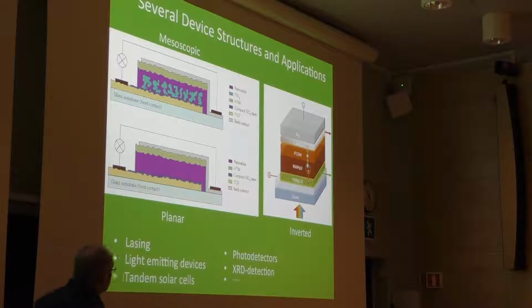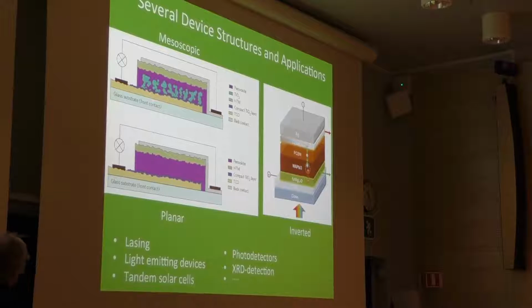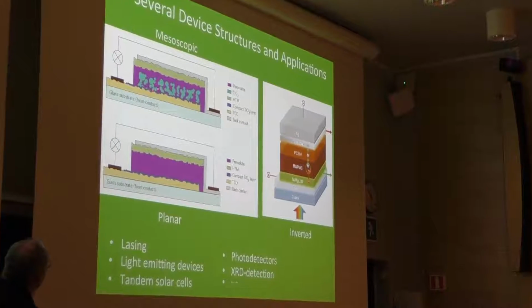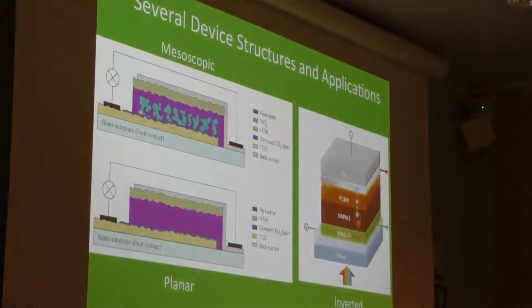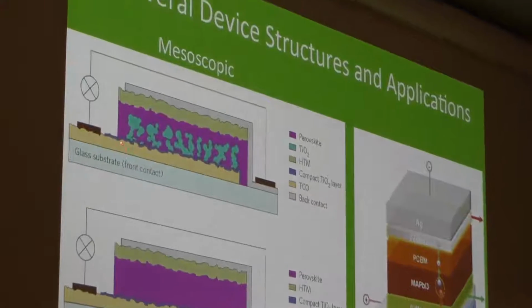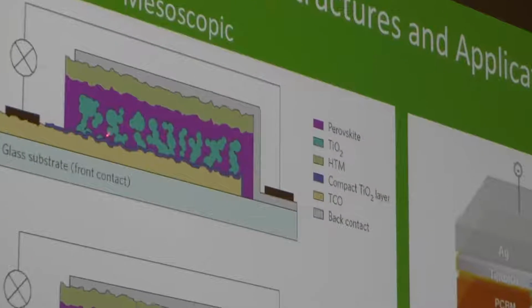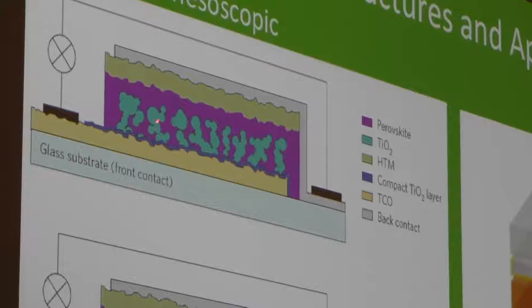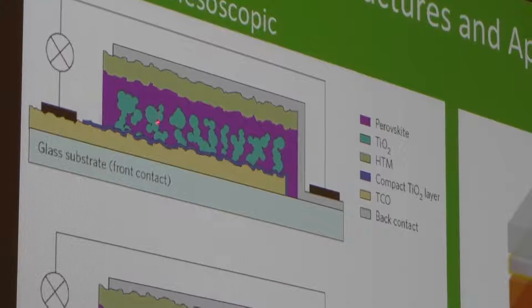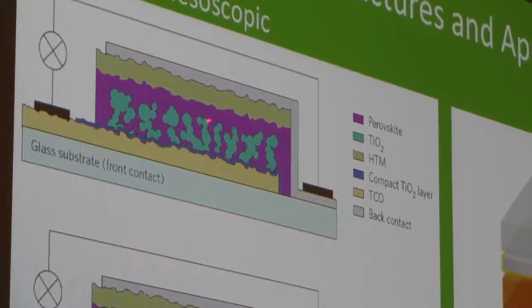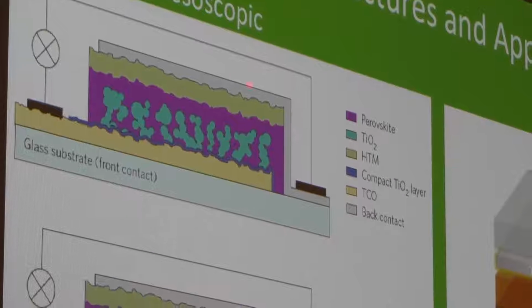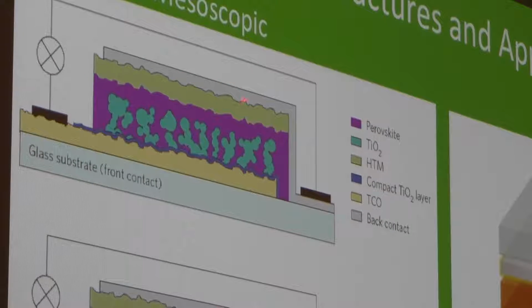So it has also been developed in different kinds of geometries. This is the starting point resembling the dye cell with a mesoporous TiO2 layer. You have the FTO glass, compact TiO2, and a very thin layer of mesoporous TiO2. We are using now 100-200 nanometer TiO2 pores. Then you impregnate with the perovskite, and then the hole conductor and gold.